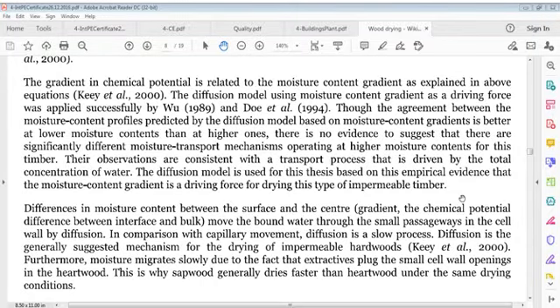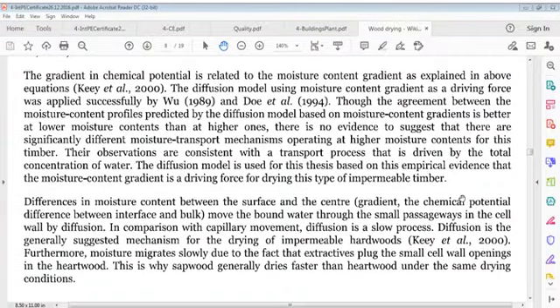Differences in moisture content between surface and center is a gradient, a chemical potential difference between interface and bulk. Move bound water through small passageways in cell walls by diffusion. In comparison with capillary movement, diffusion is a slow process. Diffusion is generally suggested mechanism for drying of impermeable hardwoods. Furthermore, moisture migrates slowly due to the fact that extractives plug small cell wall openings in heartwood. This is why sapwood generally dries faster than heartwood under same drying conditions.